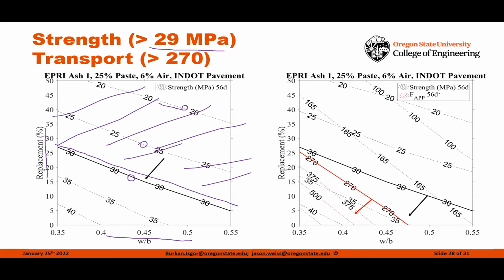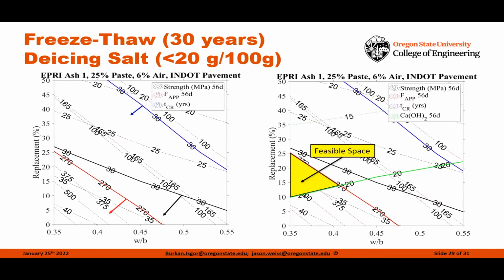We could do the exact same thing if we now start to look at our transport properties. So we can overlay contour lines for a formation factor of 100, 165, right, all the way up to a value of 500. And we can now say, here's our strength criteria. Here's our formation factor criteria. We can now start to add in some of these concepts like the time to critical saturation for freeze-thaw, which is met way up here. And if we bring in our calcium hydroxide, that actually says that everything below this green line wouldn't meet this criteria. So all of a sudden, what we've been able to do is with all of these different design criteria, we can consider them all at exactly the same time. And we can now start to define a feasible space with this particular SCM, this particular air content, that these are the mixtures that we could design that would meet this criteria.